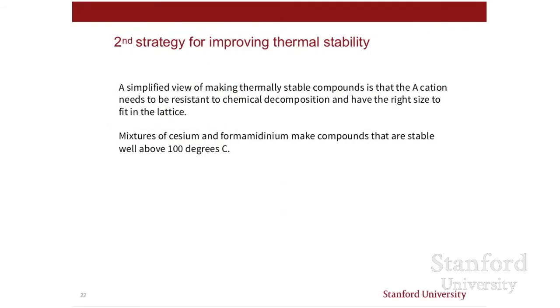So the second thing we do to keep methyl ammonium from escaping is to simply not use methyl ammonium. And if you use mixtures of cesium and formamidinium, you get a compound that we find to be stable at 150 degrees Celsius. Cesium is a little bit too small to properly fit into the perovskite lattice. Formamidinium is a little bit too large, but mixtures of the two seem to make a very robust perovskite crystal structure.